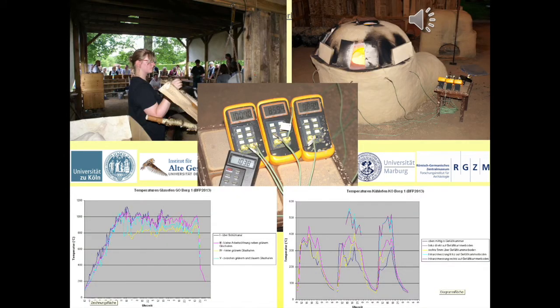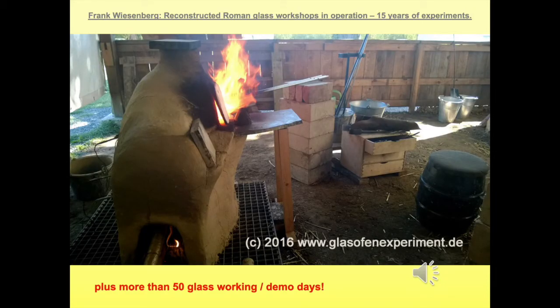During the project, a full recording of the fuel which is used for the big glass furnaces and of the temperature data, just as needed, is done. So we have comparable data from the different projects and the different ideas we did carry out at Borg. In addition to the 9 research and teaching projects at Borg, we had more than 50, maybe close to 100, glass working and demo days at the small glass furnace at Borg. I'm sorry, I lost count of them.